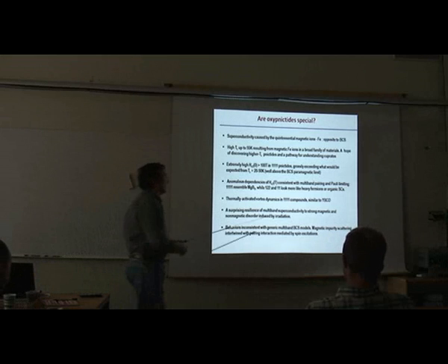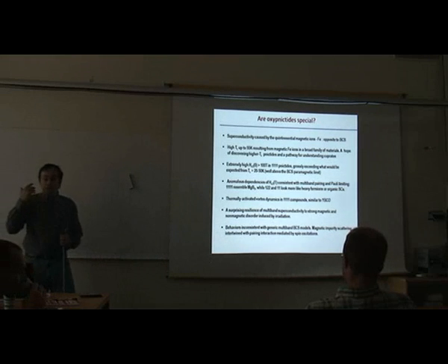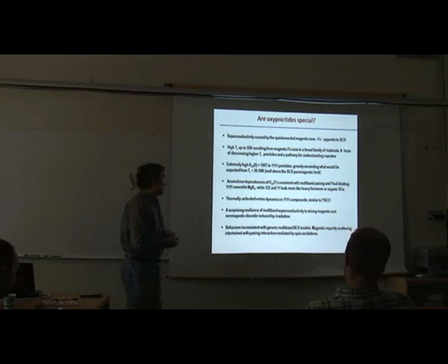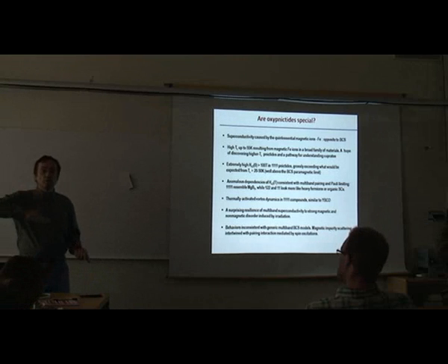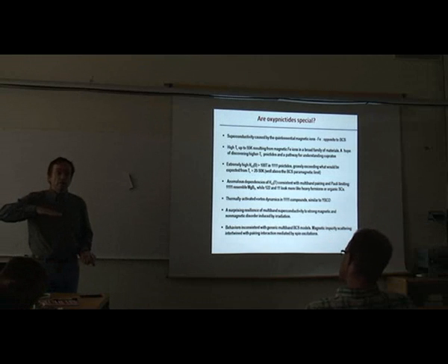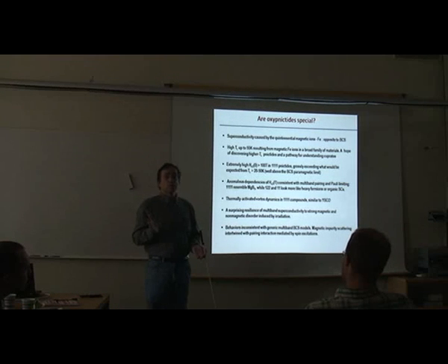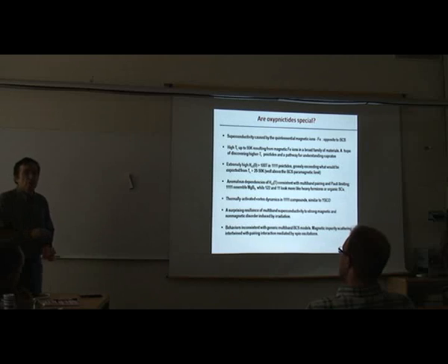And then recently we found that the response of these materials to impurities is very unusual. In fact, we can irradiate this with heavy ions and produce very uniform distribution of impurities, and the response is very unusual. Actually, these materials can tolerate a lot of disorder without strong Tc suppression. And that is really unusual given that the current models basically all assume that these materials have unconventional pairing symmetry.